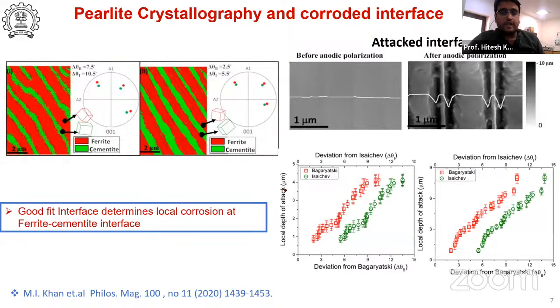As it is increasing, it is basically increasing the local depth. The question is how we calculated the local depth with the help of AFM, because we calculated the roughness of the material at the particular colonies, as well as with a Zeta profilometer. So we went to each colony and, with the help of EBSD, calculated the Isaichev and Bagaryatski interface relationship, as well as how much depth, how much material is removed during the corrosion.